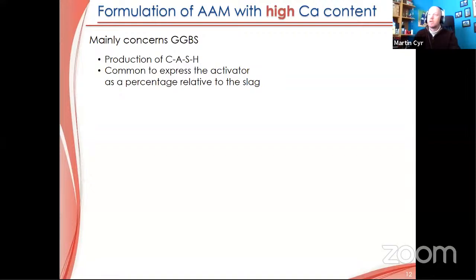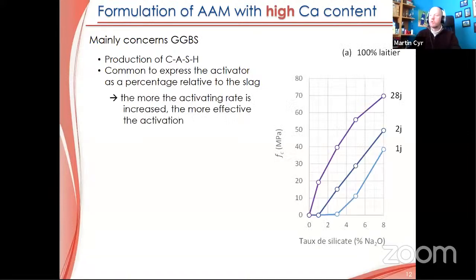So if I have a look at GGBS, for instance, as I told you, we have the production of C-A-S-H. It is well known. It is quite common to express the activator as a percentage relative to the slag. It is working quite well because we are still in the calcium chemistry. So this one is much easier to manage. And usually what we see is the more the activating rate is increased, the more effective is the activation itself. You can see it here with a 100% slag.